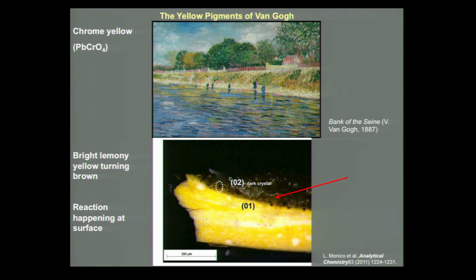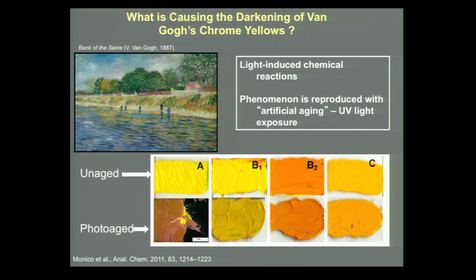Okay, so if we look at a cross-section of the chrome yellow paint, at the bottom everything looks really good. We have the bright lemony yellow color that we would expect, but at the top things really are not looking so good. We have these dark brown crystals forming. So in terms of what's causing the darkening of the yellow pigment, it turns out that it's light-induced chemical reactions. And the reason we know this is that we've been able to reproduce the phenomenon using a technique called artificial aging, essentially ultraviolet light exposure over a short period of time.